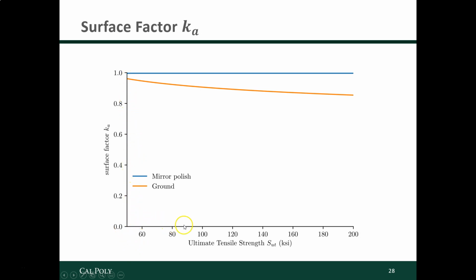As the steel gets stronger and stronger, stronger steels tend to be a little bit more brittle, right? A little bit less forgiving of cracks, especially near the surface. And so if you have a ground finish, it's a little bit less pristine. You could have tiny micro cracks, little imperfections that turn into big cracks as you apply cyclic loads. They open up over time and eventually the whole material fails. And so that's why when you've got a less than perfect finish, then especially as you have a little bit less forgiving steel, you end up with a lower surface factor and a lower endurance limit as a result.